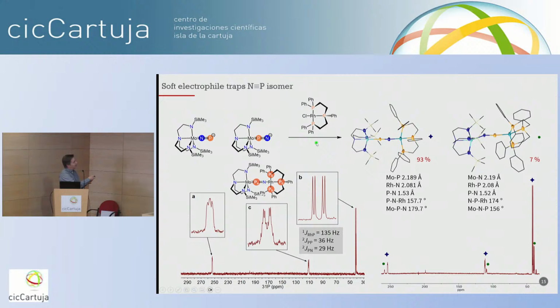If you add this rhodium-1 complex to this mixture, then you get mainly this complex here, but you also get a little bit of this, about less than 10% occupancy in the crystal structure. We can see this by NMR very nicely in the phosphorus NMR. The diamonds here correspond to the major isomer, with a very nice coupling pattern, but then the circles here correspond to this guy here. And we could assign all the resonances in the phosphorus NMR for the major isomer quite nicely.